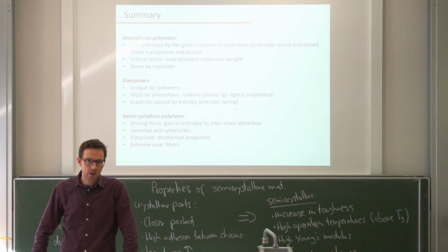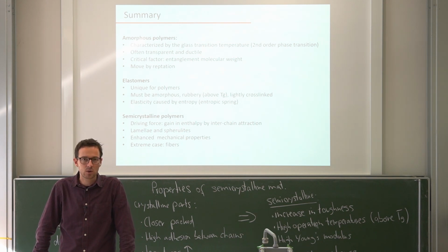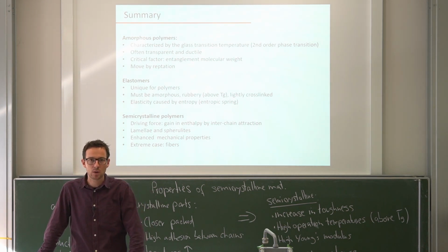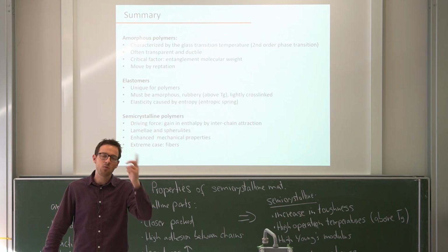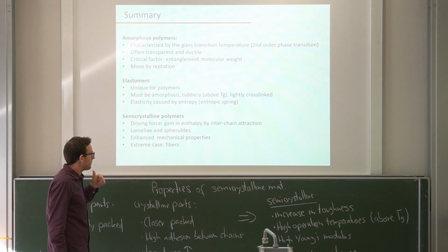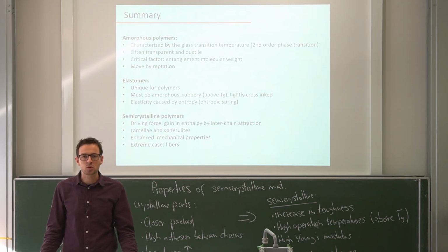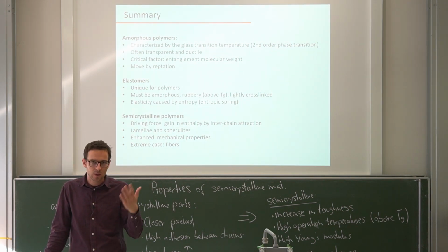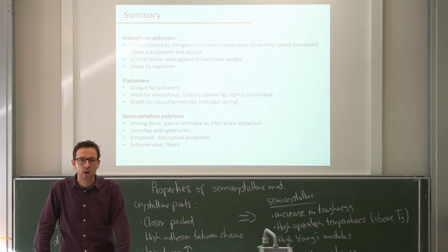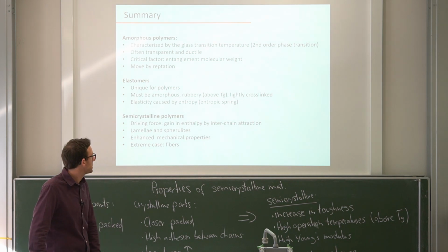And they can be atactic, which is random, this cannot crystallize, isotactic, where all side groups point in the same direction, which then can crystallize, or syndiotactic polymers, where the side groups alternate between the positions. Then we've seen that we can use hydrogen bonding, which is probably the most typical way of achieving something like this, and that's kind of the key trademark of nylon or polyamides. But we can also use more exotic interactions such as pi stacking to create a polymer crystal, which is very important in organic semiconducting materials.